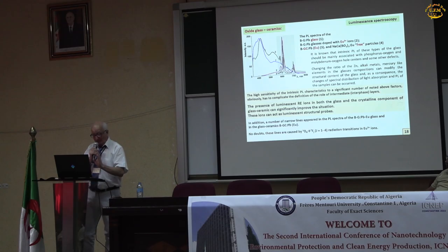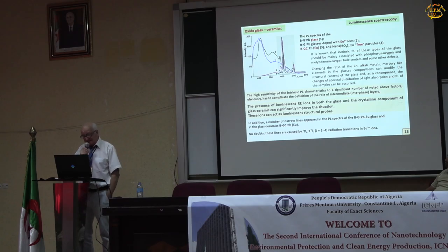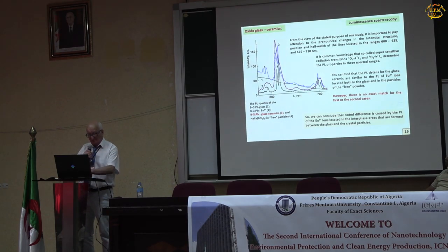And we see the high sensitivity, I try to emphasize, the high sensitivity of the intrinsic photoluminescence characteristics to a significant number of noticeable factors that complicate the definition of the role of intermediate interface layer. But the presence of luminescent europium ions in both the glass and the crystalline component of glass ceramics can significantly improve the situation. These ions can act as luminescent structural probes. So we see this spectra in detail.